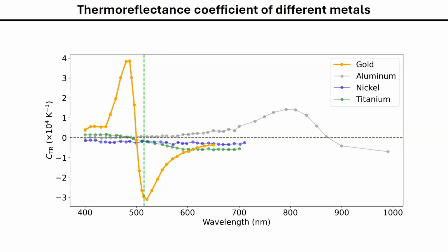First of all, our setup was limited to these two wavelengths. We have a fundamental laser centered at 1030, and we can produce the frequency doubling, so half the wavelength, 515 nanometers, which is green. If we look at the available metal transducers used in the literature, we can see that most experimental studies are using their probe at 800 nanometers. This is the wavelength of the titanium sapphire laser, and therefore it's very common, and so it is available in several labs. So the typical choice is aluminum. Also, aluminum has a large electron-phonon coupling, and so heat thermalizes very quickly.